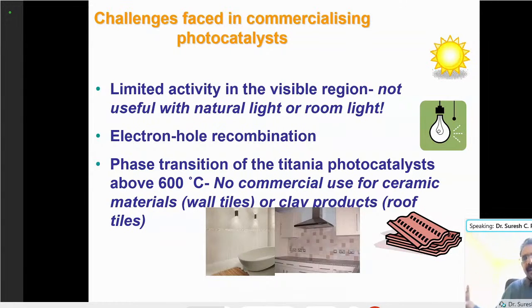One classical example is ceramic tiles, bathroom tiles. If you want to coat these materials on ceramic tiles, you have to make these materials stable at high temperature. Why? Because during the manufacturing process, these tiles are sintered at very high temperature, up to 1000 degrees Celsius.